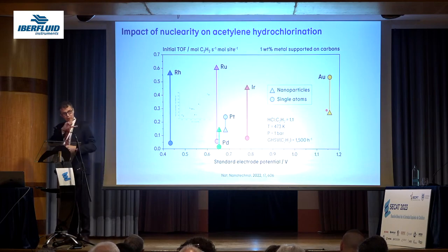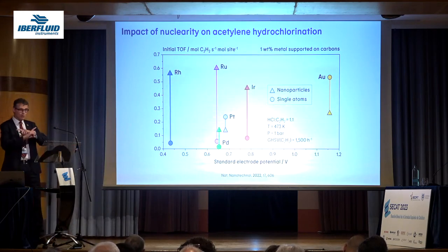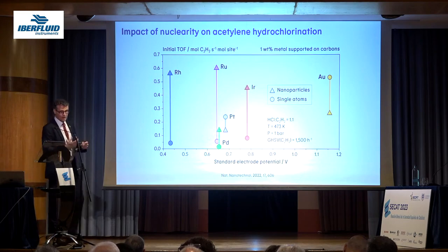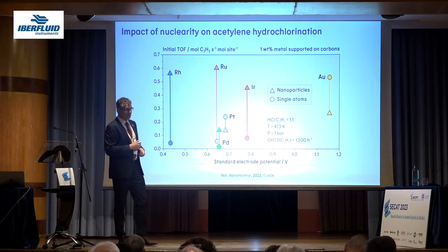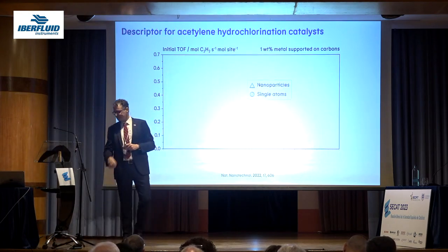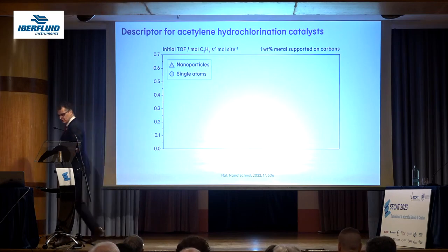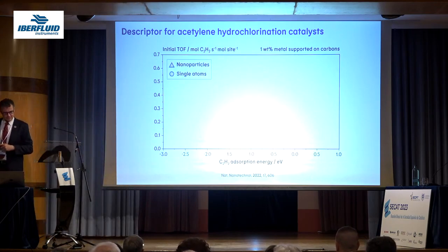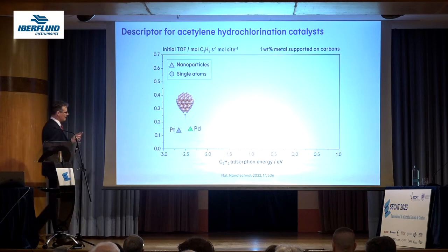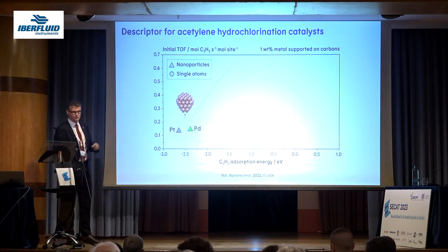So what happens is that the correlation line actually is the box of the graph. There is no correlation. And that means that the electrode potential is a wrong descriptor. A better descriptor to do this is the adsorption energy of acetylene. So we have been working a lot because that is sensitive to the nanostructure. So what we could see is there is a volcano plot dependency where the optimal adsorption energy of acetylene is for ruthenium and rhodium nanoparticles and gold single atoms.